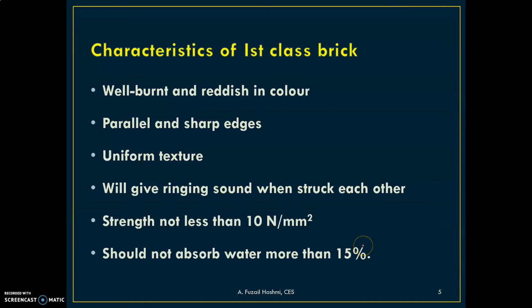So, when this first class brick is immersed in water for about 24 hours, it should not absorb water more than 15%. And the compressive strength of the first class brick should not be less than 10 Newton per mm square. And one more point is that when these bricks fall from a height of 1.5 meters, they will not break down. So please remember all these characteristics.